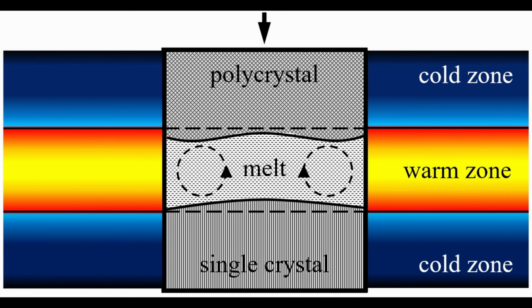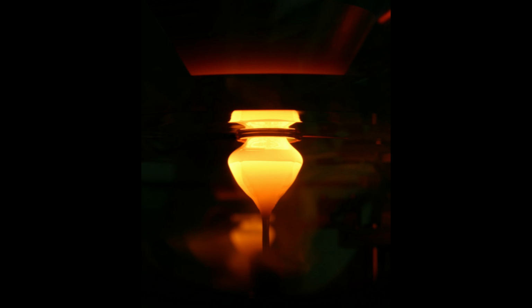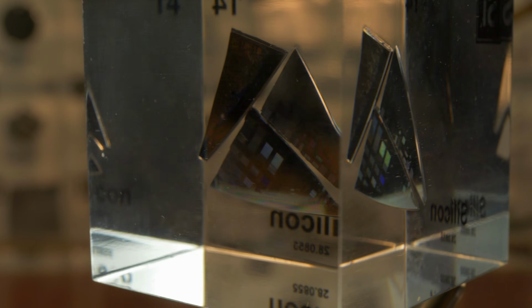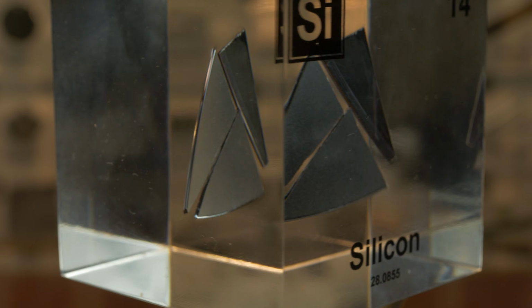Another method for ultra-high purity single crystal is zone refining, or the float zone process. In zone refining, a rod of silicon is passed through a heating coil that melts a small region at a time. As this molten zone moves along, it carries impurities with it, leaving pure silicon behind where it re-solidified. Repeating this can push impurities to one end of the rod, which is then cut off. Float zone can achieve incredibly low impurity levels, even better than the Czochralski, sometimes because the crucible in the Czochralski process can introduce a bit of oxygen from the quartz. Float zone silicon is often used for special high power or sensor applications.